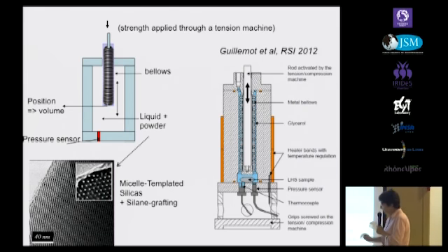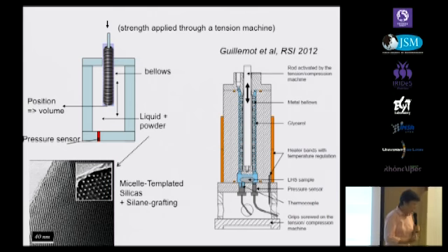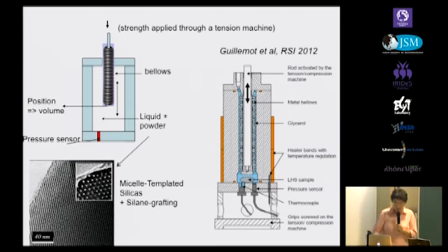The porous volume of this material is made of cylindrical pores which are not connected to each other and which have a small dispersion in pore size, so a well-defined radius.